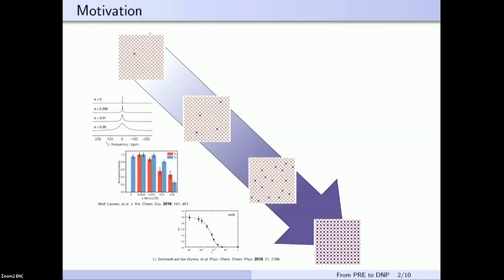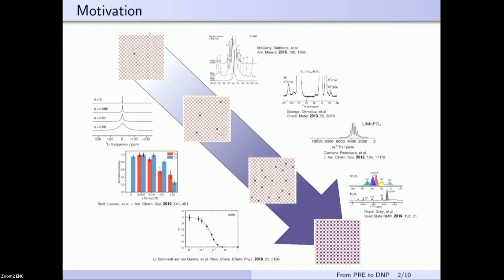We just saw Gillian's talk where she was showing us lithium-7 spectra of lithium-7 nuclei that were sitting nearest neighbors to paramagnetic iron. So the fact that she was able to observe the spectrum means that they are actually able to see all the nuclei in the sample. So there's no quenching at all.